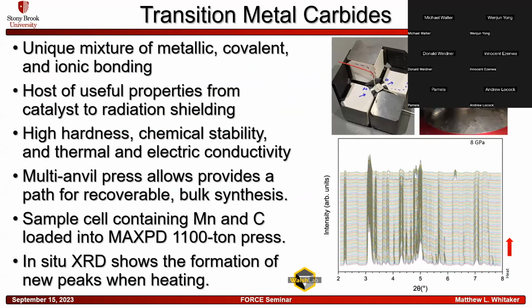So one of the other things that we've done very recently is the synthesis of transition metal carbides. That's been a very large thrust at the beamline. The reasoning behind this is that there is a unique mixture of metallic, covalent, and ionic bonding in these materials. And they have a host of useful properties, from radiation shielding to catalysts to hard materials. They have very high hardness, chemical stability, and very good thermal and electrical conductivity. So the multi-anvil press allows us to have a path for recoverable bulk synthesis of these materials.